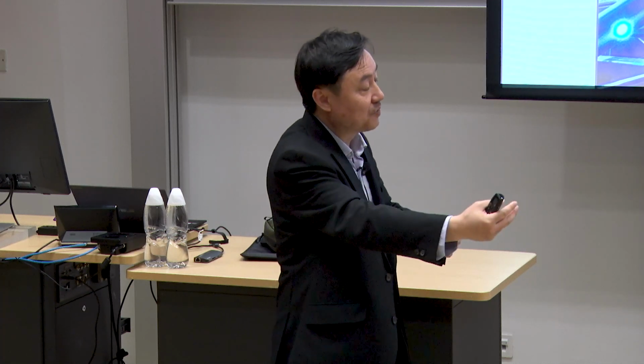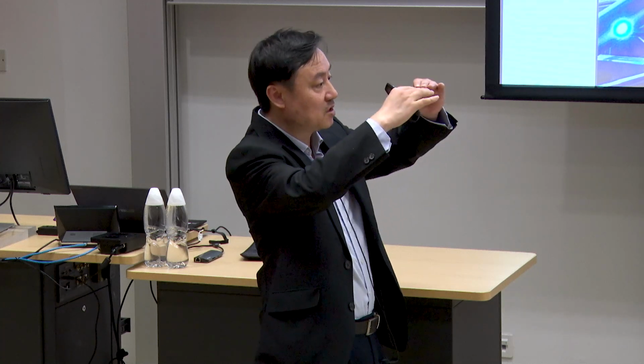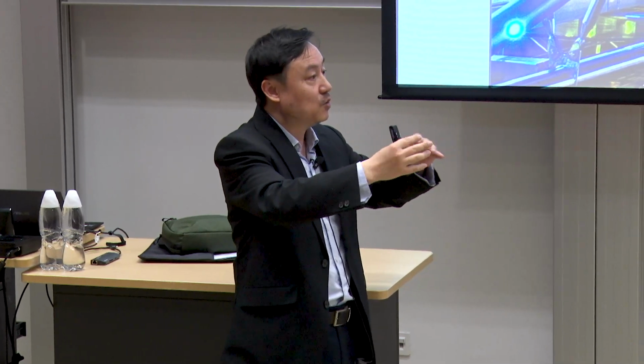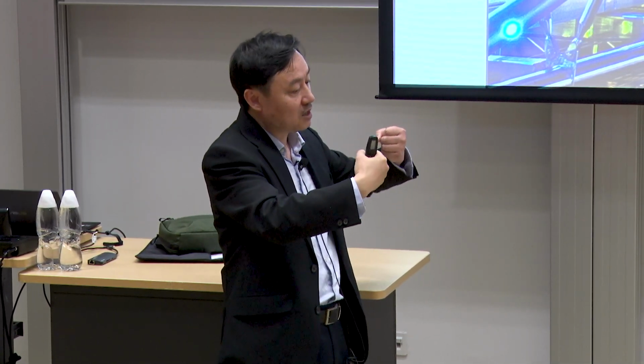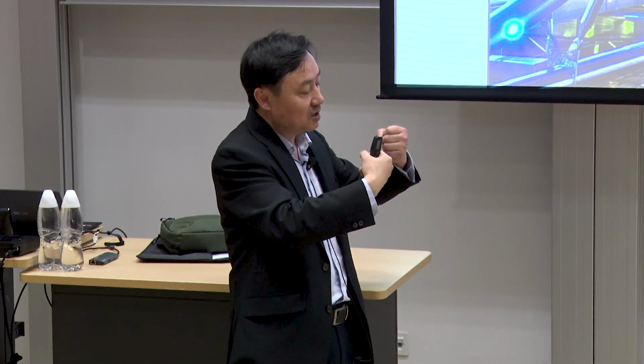But energy migration is a special case of energy transfer. So this is unlike FRET. FRET typically doesn't accept it. So this energy migration, like I said, is more like you have the Gd ions within the lattice, so they are at very close distance. It's more like a resonant energy transfer through the Gd ions. The Gd ions' electron energy level is about 4 electron volts, so they are pretty stable. Even water will not quench that. So through the Gd, I think it's an elastic energy transfer. One Gd transfers to another Gd, more like a resonant transfer, then goes through the lattice.